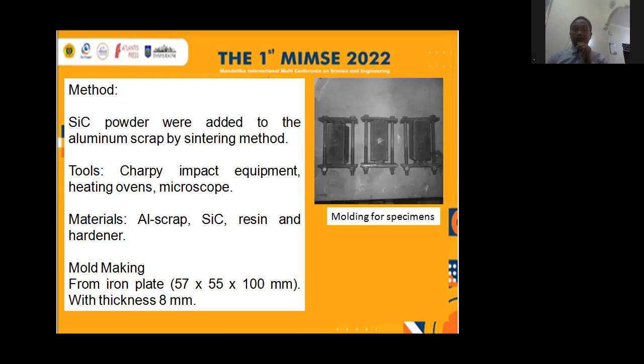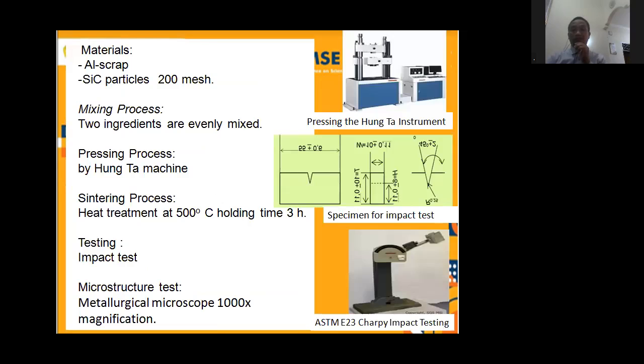The mixed material is aluminum scrap with silicon carbide, which has been sieved beforehand to a particle size of 200 mesh. The pressing of the materials is carried out with a Hung Ta instrument machine, with a maximum pressure used of 150 kilonewton.